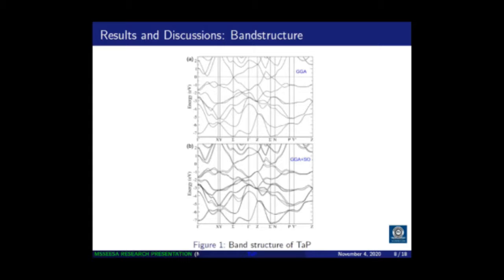Now, in this graph, there are two figures. There is figure 1, the band structure which I computed without the spin-orbit coupling so that I can observe the band structure of this particular system. And as I mentioned earlier on, this tantalum phosphide has a Weyl fermion. A Weyl fermion is where two bands meet, they touch near the Fermi level. So I can see at this particular point the bands are touching, and the dotted line is the Fermi energy for this particular structure.